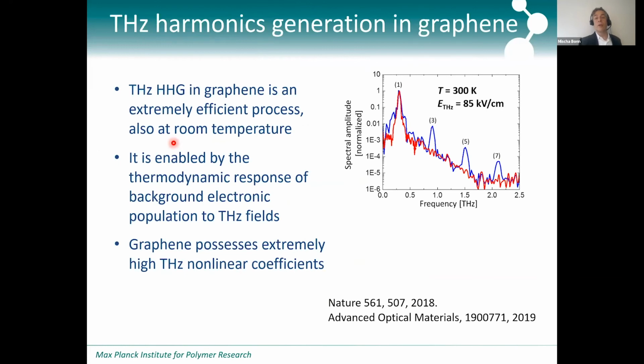So what I've shown you is that we can very efficiently generate higher harmonics using a single layer of graphene at room temperature. This is enabled by this very high polarizability of the free electrons, and the nonlinear optical coefficients are stellar. I mean, they're unprecedented.